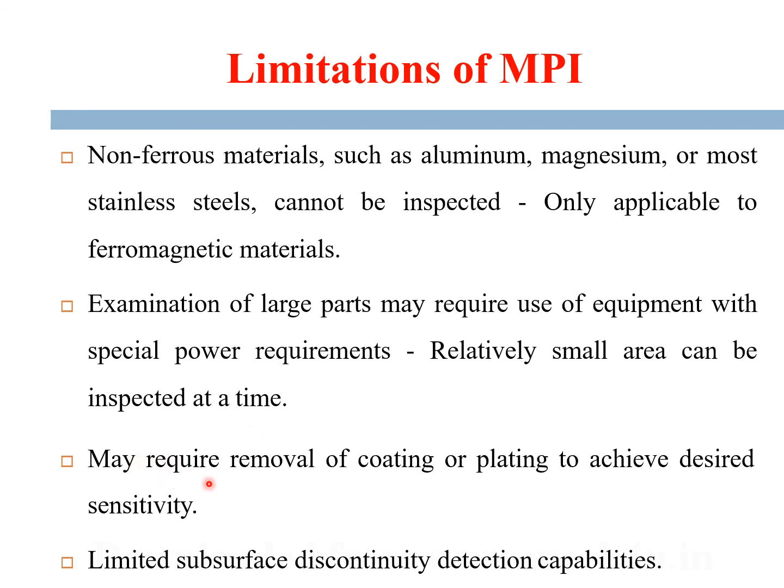And it may require removal of the coating or plating to achieve the desired sensitivity. That is, certain surfaces will be coated or plated. For such surfaces, it is difficult because you have to remove it completely and only then can it be tested. Then there are limited subsurface discontinuity detection capabilities, because just below the surface you can easily find the discontinuities, but in-depth cracks or inner cracks cannot be easily detected.